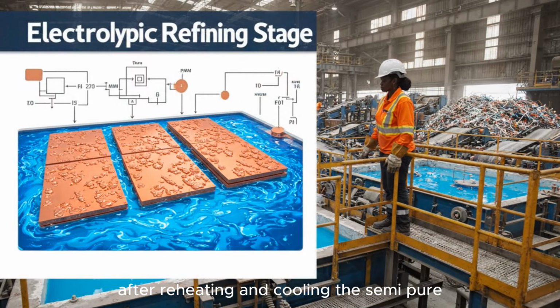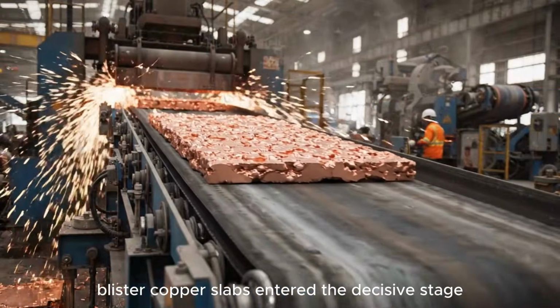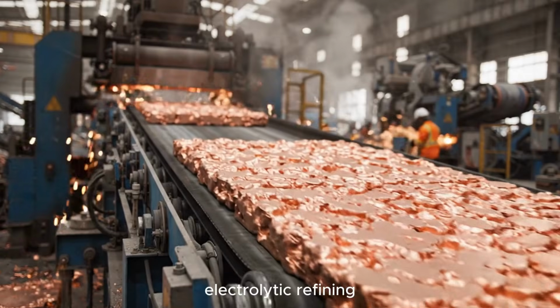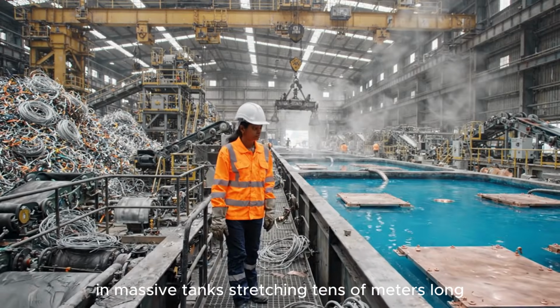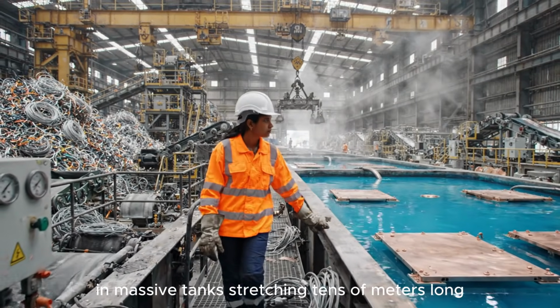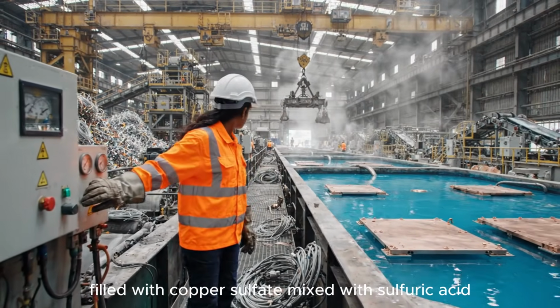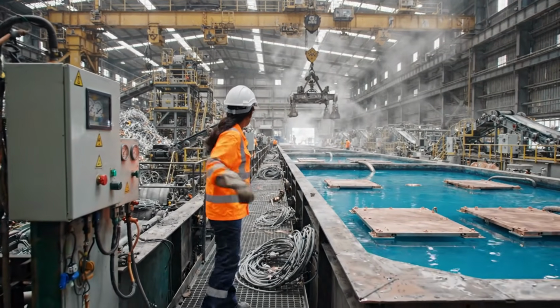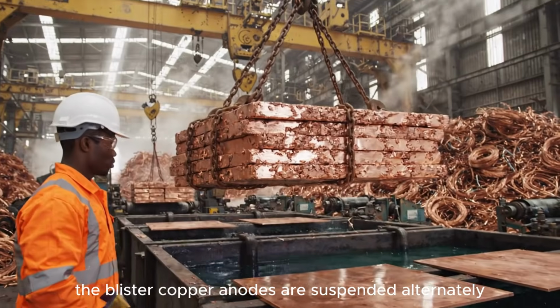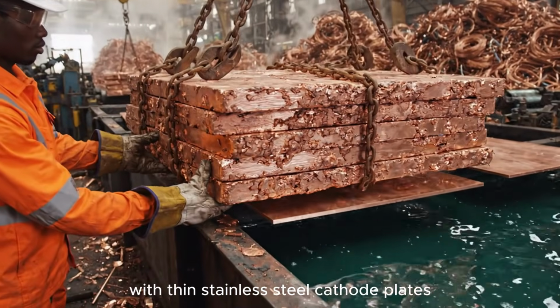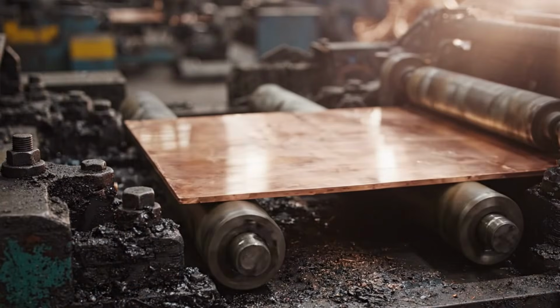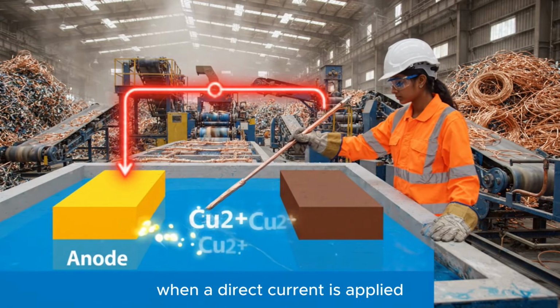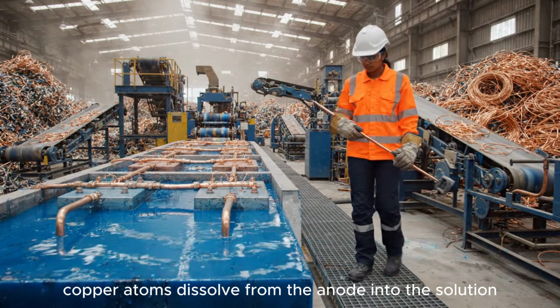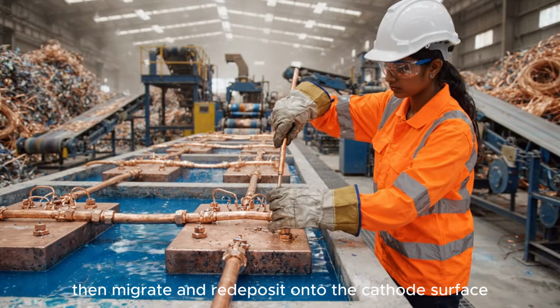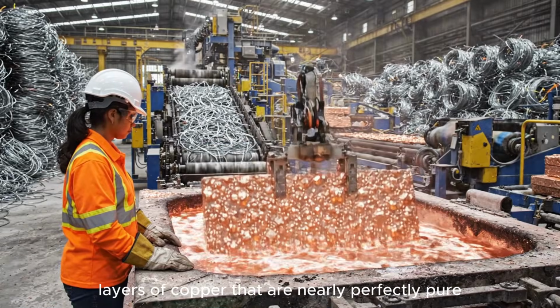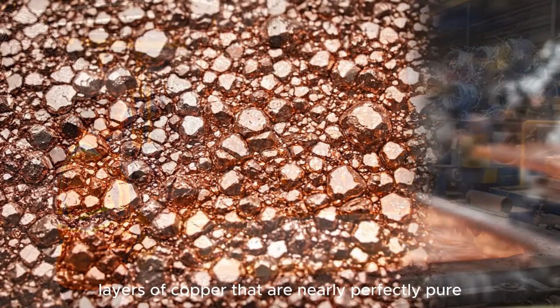After reheating and cooling, the semi-pure blister copper slabs enter the decisive stage, electrolytic refining. In massive tanks stretching tens of meters long, filled with copper sulfate mixed with sulfuric acid, the blister copper anodes are suspended alternately with thin, stainless steel cathode plates. When a direct current is applied, copper atoms dissolve from the anode into the solution, then migrate and redeposit onto the cathode surface, forming layers of copper that are nearly perfectly pure.